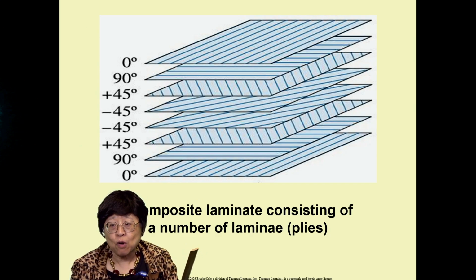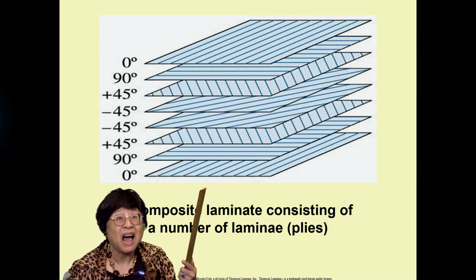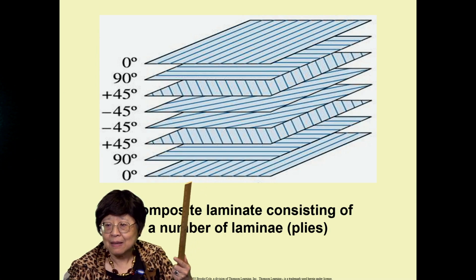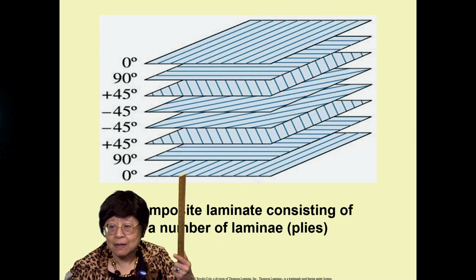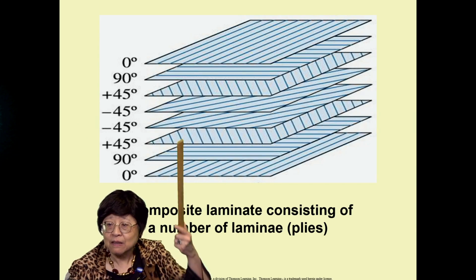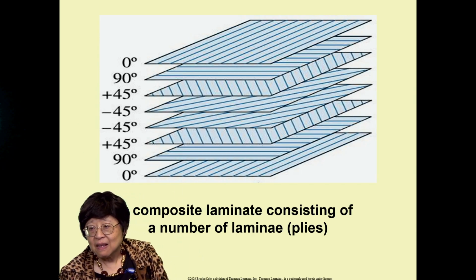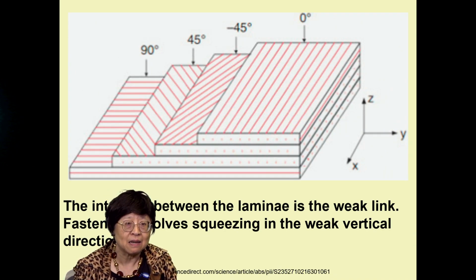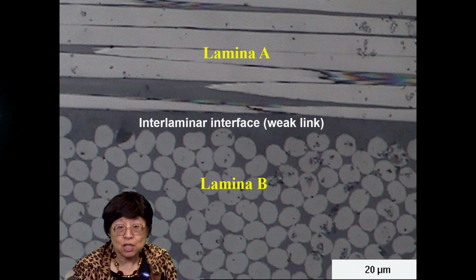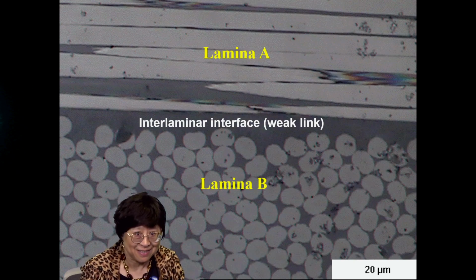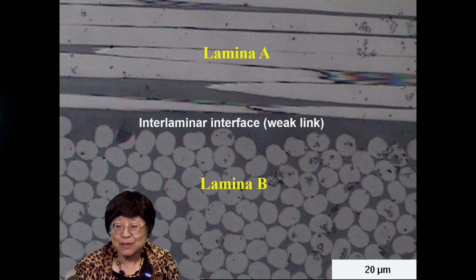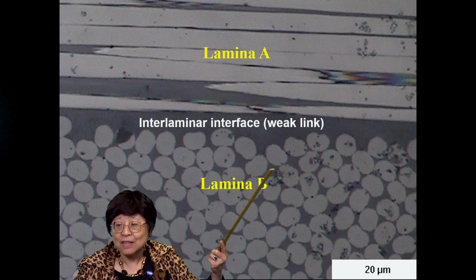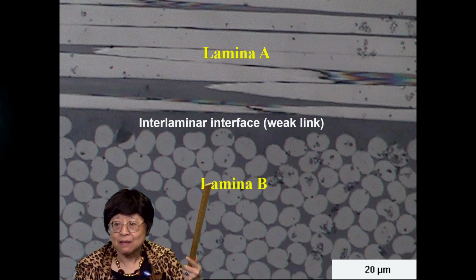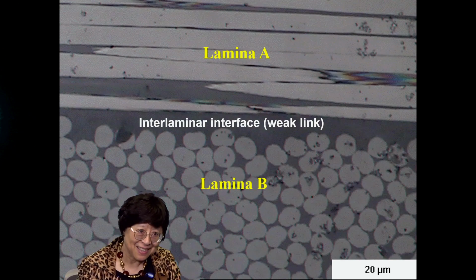These composites are in the form of laminates, that is, they're in the form of plies, or called laminae. Within each ply, the fibers are in a certain orientation, and in different plies, they are in different orientations. And between the plies, that interface is the mechanical weak link. Okay? And so in fastening, you are squeezing along the weakness direction, squeezing in a direction perpendicular to this interlaminar interface, the interface between the two plies. No wonder there's a problem.